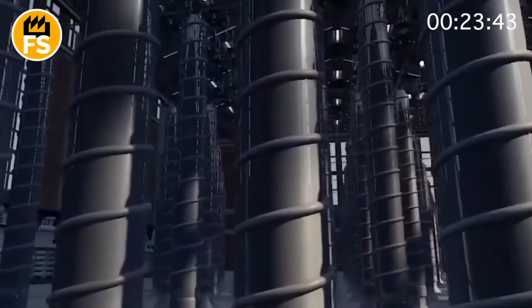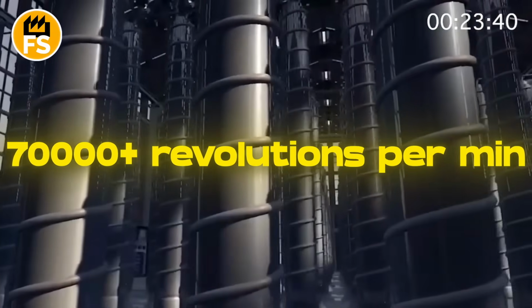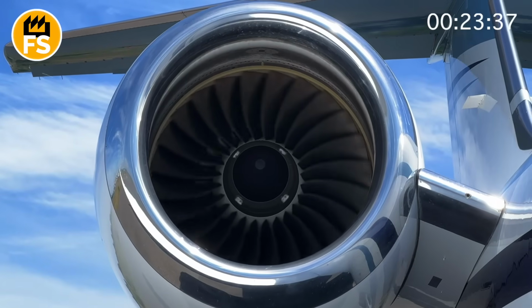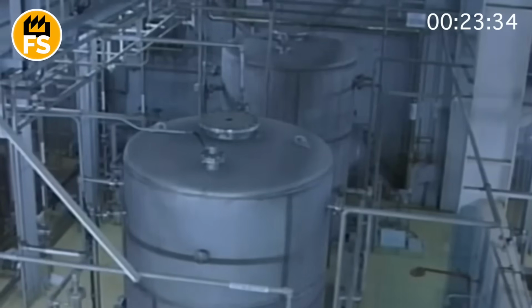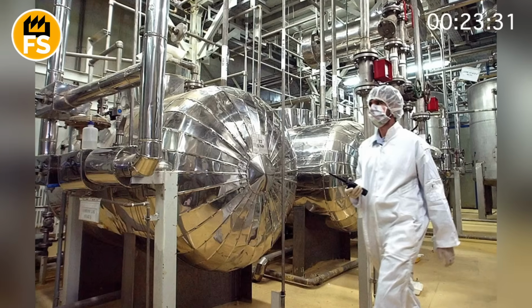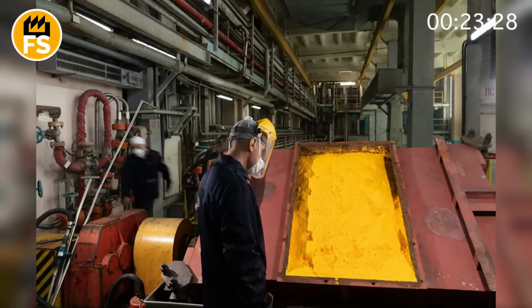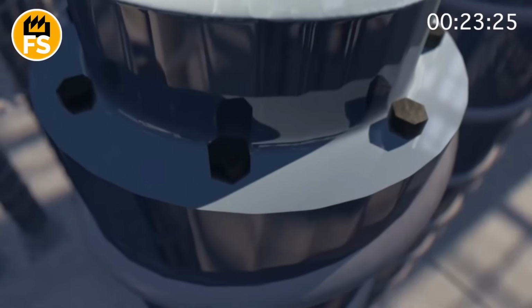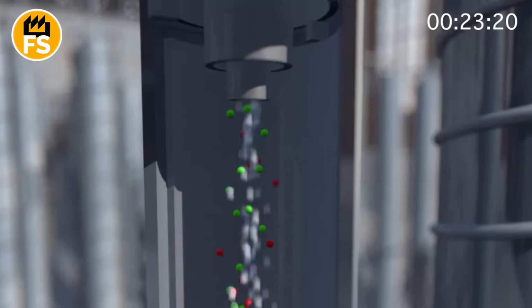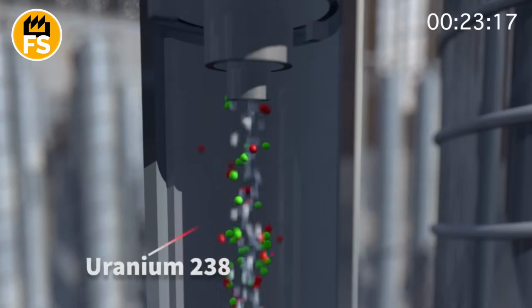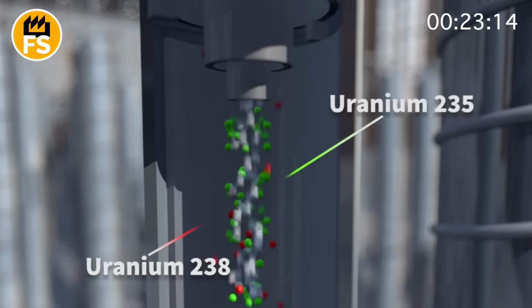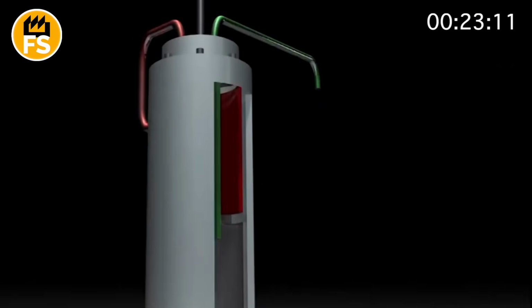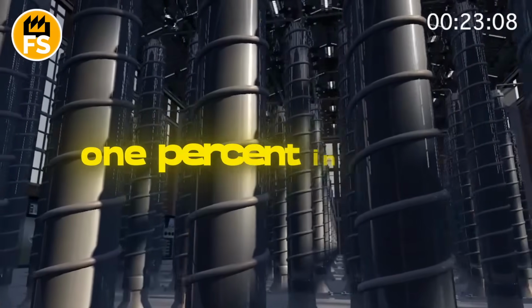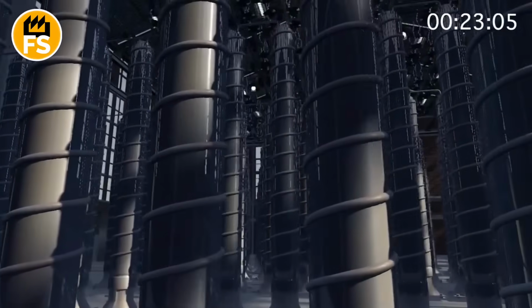You think spinning a washing machine is fast? You haven't seen nuclear centrifuges that do 70,000 revolutions per minute. That's 10 times faster than an airplane turbine. And all for one thing, to separate uranium isotopes. The uranium hexafluoride, that same poisonous gas we just made, is pumped into a tall, narrow cylindrical chamber, which is spun up to an insane speed. Centrifugal force does its thing. The heavier U-238 atoms fly to the edge, while the lighter U-235 atoms stay closer to the center. A tiny, microscopic difference, 1% in mass, and all this explosive technology spins just for it.